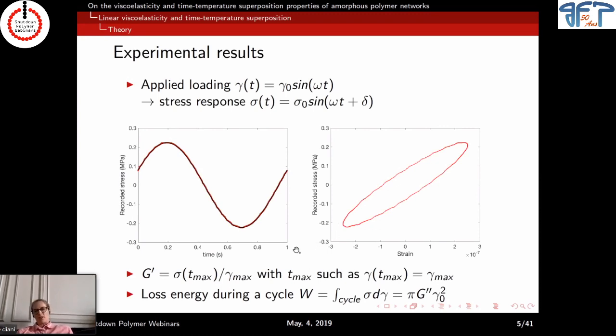G prime and G double prime are calculated using fast Fourier transform, but you can also define G prime very simply like that. It's stress when the strain is maximum over the maximum strain. And G double prime is related to the energy loss during a full cycle. So the hysteresis on this ellipse.